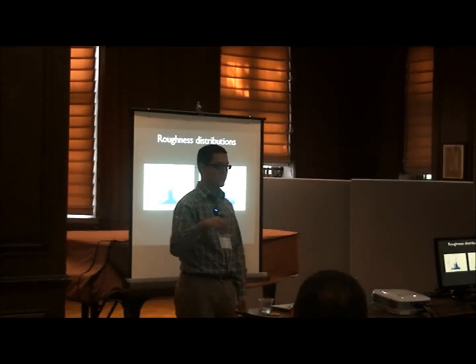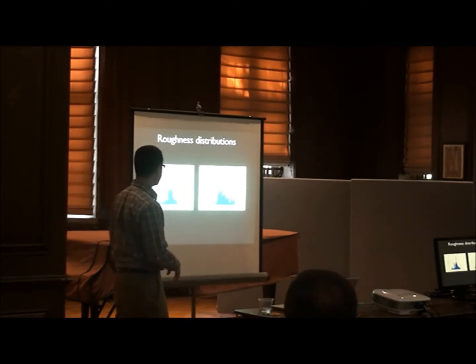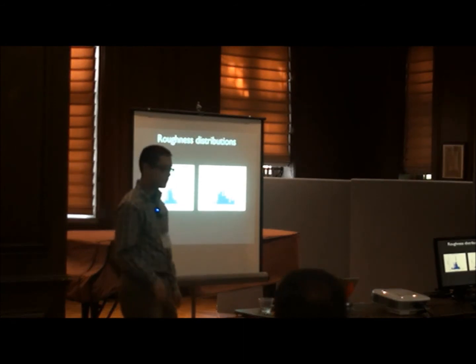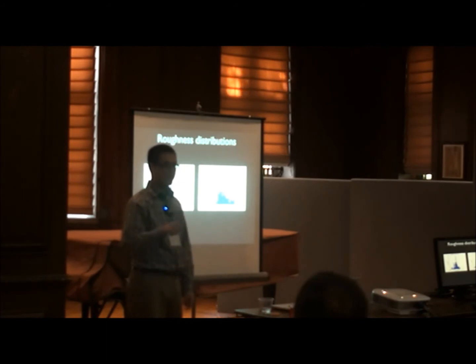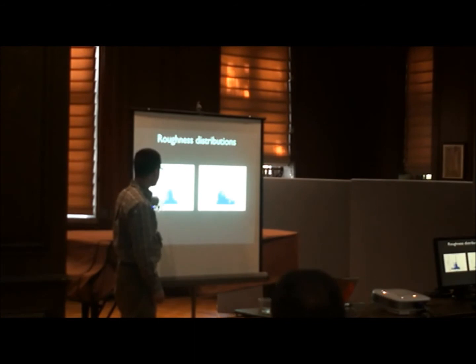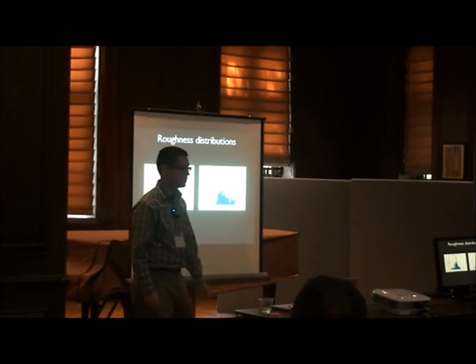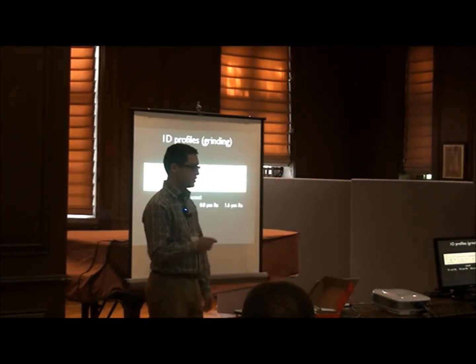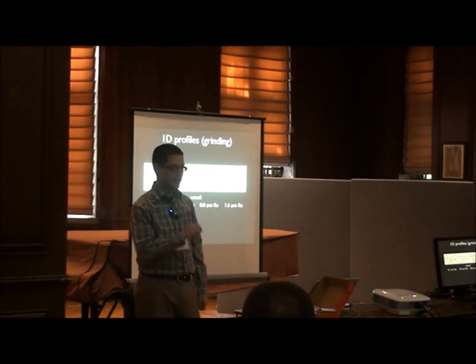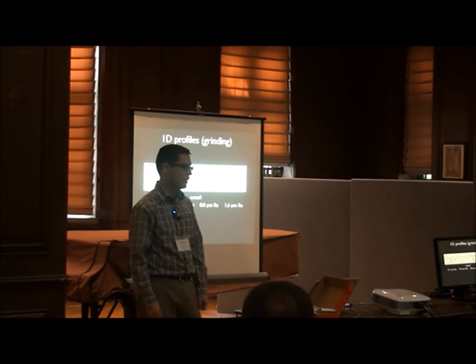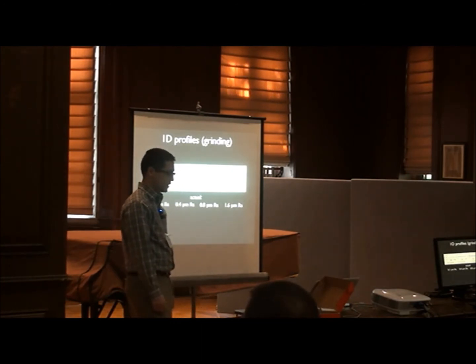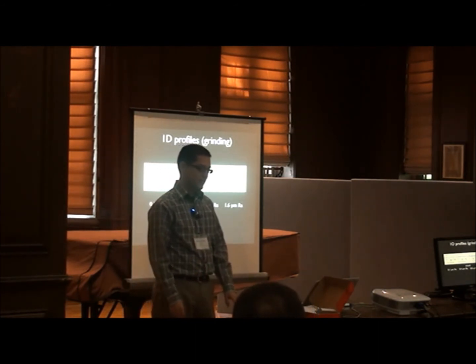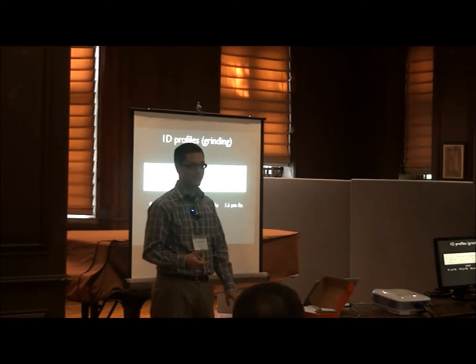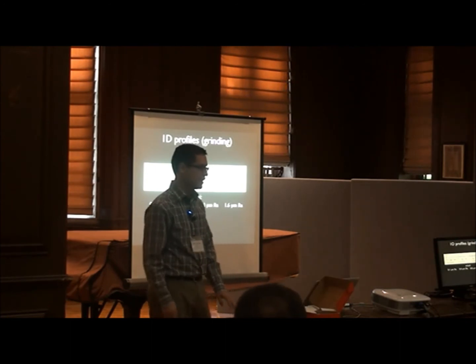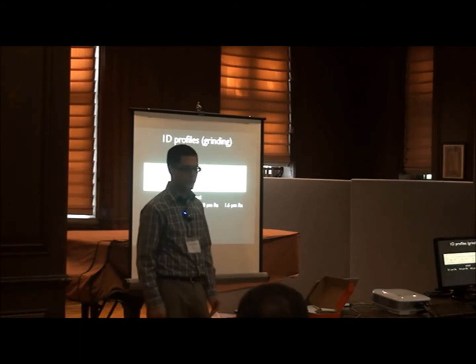We also did a bunch of roughness measurements over different areas on those patches, and they form a distribution. This was not a very high quality surface roughness gauge, so I really don't believe at every location it's very close to its nominal roughness, but you can see the distribution is at least peaked in a region relatively close to what it should be. We can also get scan lines, right? Although we're making an image or measurement of an area, you can take scan lines out, which would be comparable to what you get with a stylus-like device. And one of the customers we're working with has made the argument to his bosses that this device can measure 1,000 scan lines, 1,000 1D profiles, instantaneously. So it's as if you had your stylus gauge and you made 1,000 measurements all within a second. And that is an advantage of having a surface measurement rather than just a single 1D measurement.